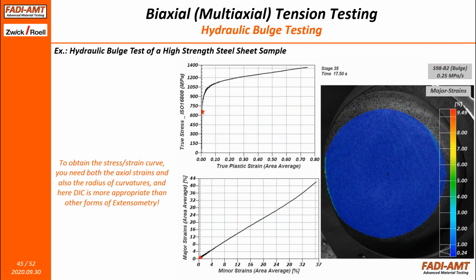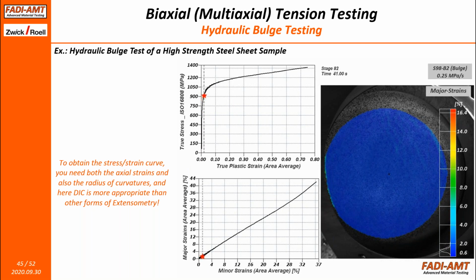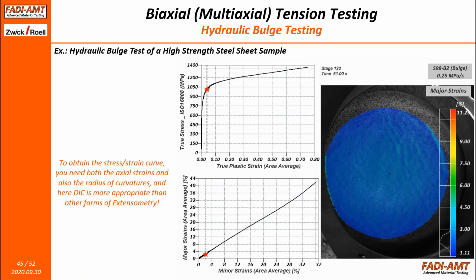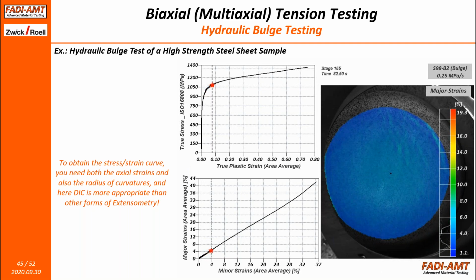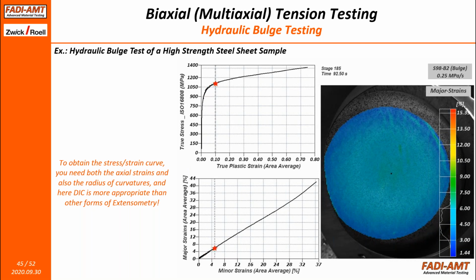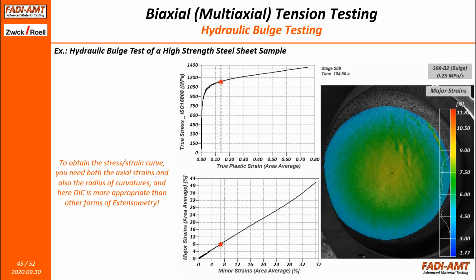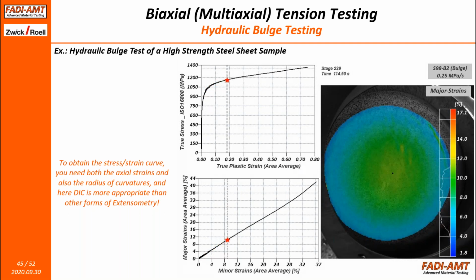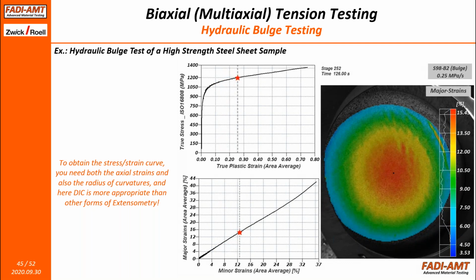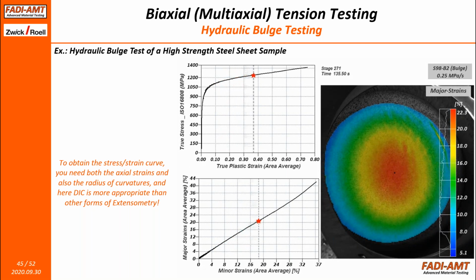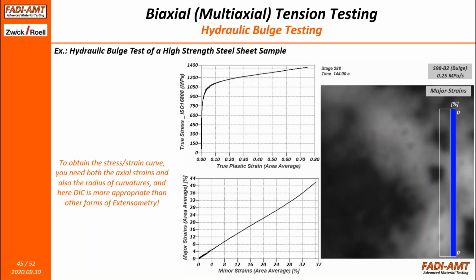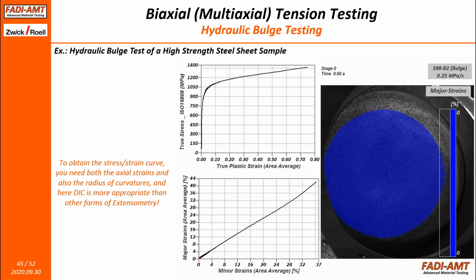This is a video example of a typical hydraulic bulge test that we perform on high-strength steels. You can see in the video that we constructed, on the top left, a stress strain curve for this material. And this is where DIC is unique. If you're just measuring the strains in the X and Y in the bulge test, then you can do it with conventional extensometry. If you truly want to construct the stress strain curve, then it's much easier and more accurate to use digital image correlation, as shown in this video.